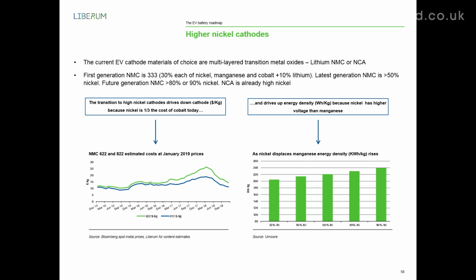What is that transition about? It's really about 2 things. It's about replacing high-cost cobalt with nickel at 1/3 of the cost, and it's about replacing low-voltage manganese with higher voltage nickel. And the transition is effectively driving two things: an improvement of energy density at the cell level, which we think is around about 20%, and an improvement in cost depending on the cost of nickel and cobalt metals, which we think is going to be in the region of 10 to 20%. So overall, combine those two, and you have an improvement in the overall cost per kilowatt hour that could be in the range of 30 to 40%.